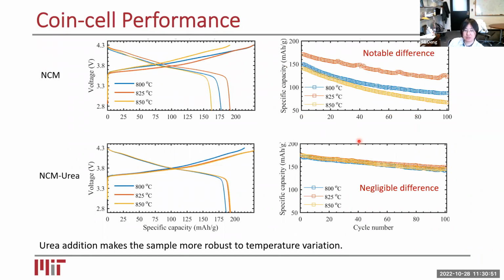And before I dive into the proposed mechanism of why things work, to complete our test, we also did this coin cell performance. And as I indicated in the thermal XRD, you can see that without adding urea, we do see a notable difference if we change the annealing temperature by 50 Celsius, for example. You do see the capacity changes a lot. However, for this new material with the urea added in the precursor, where afterwards the urea is gone, it's decomposed, we do not see differences, giving us hope to expand the annealing temperature region.